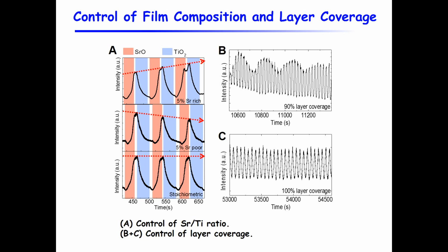And this is very similar to what MBE people are doing by opening up different shutters, except that here we are using the laser pulses. And exactly the same way as what Shalom demonstrated, you can monitor the RHEED intensity oscillation to control whether you have one-to-one strontium to titanium, or too much strontium, or too little strontium. And so that can help control whether we have the right ratio between the two elements.